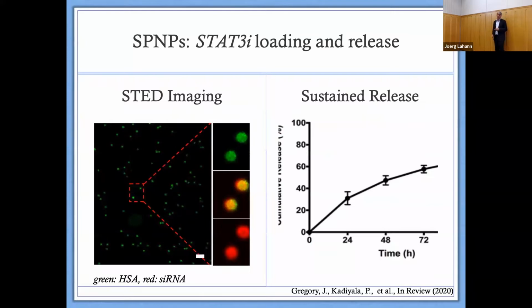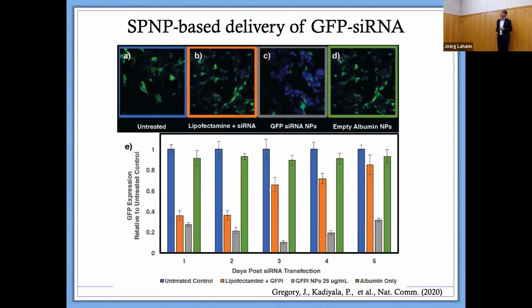So that's nice. And that's not so easy with small particles. I mean, think about what the diffusion time of a small molecule over 100 nanometers is. What do you think if it's rediffusing? Probably seconds, right? So you do have to have processes to sequester and control that release. So it works with GFP siRNA. That was our first test case. The paper also uses STAT3, obviously in vitro, but I just want to show it looks nicely and it works similar to lipofectamine, maybe in this particular case, even a little bit better.